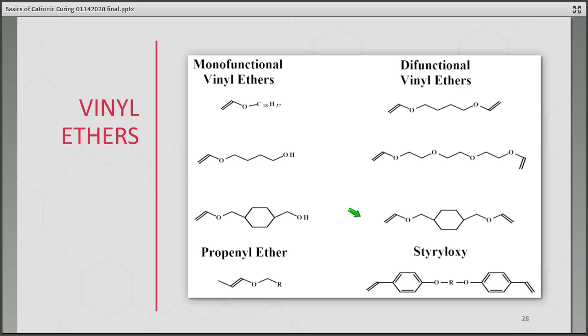You can also use vinyl ethers in your formulation. Here's a range of different ones that have been used in the past, both monofunctional vinyl ethers and difunctional vinyl ethers. These were very popular and very common, I'm going to guess, say 10, 15 years ago in UV curable cationic chemistry. They're used less so now, primarily due to lack of availability. Some of the suppliers have moved on to other materials and are no longer making these materials, so it's a little bit harder to get a hold of.